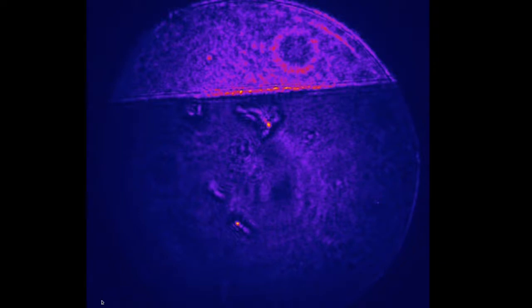Okay. So I'll just give you one teaser where we combined both an imaging technique and an X-ray technique. Many of the diagnostics you've seen in the other hard X-ray instruments work here. So this is, for example, an imaging technique where we looked at a shock wave as it propagates through a sample. Here you have a silicon wafer with a thickness of about 100 micron, and the X-rays go perpendicular to the screen here. On the top edge of this wafer, we shoot our optical laser. A shock wave will propagate through this sample, and with the X-rays we take snapshots about every nanosecond.